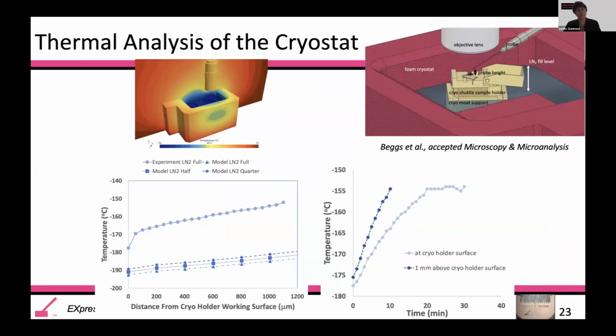So just to show you that, again, this works via transfer of the system in the cryo vapor phase. We've looked again at the heat transfer. This is a temperature as a function of distance from the cryo holder working surface. And what we can see is that well over a millimeter above the surface, we remain below the vitreous temperatures. And in fact, this liquid nitrogen at this level will last for tens of minutes.